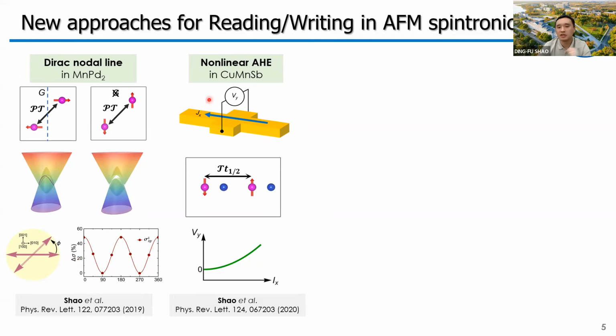And we also found in some non-centrosymmetric antiferromagnets, we can have a Néel vector dependent nonlinear anomalous Hall effect. These effects are very interesting, and because there are strong responses against the Néel vector rotation, we can use these effects to detect the Néel vector in compensated antiferromagnets. However, these effects, together with the anomalous Hall effect and anisotropic magnetoresistance effect I mentioned on the previous page, are all associated with the spin orbit coupling of antiferromagnets itself.